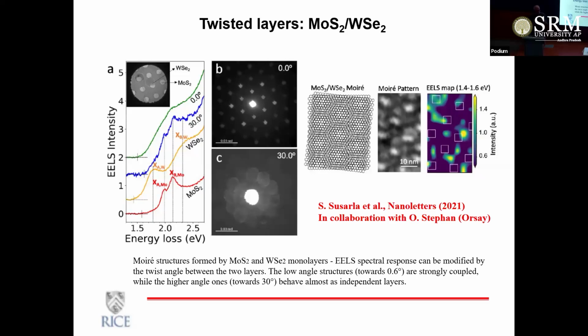You wouldn't typically imagine that twisting two films would be called engineering, right? But when the thicknesses are at the atomic scale, then you start to see significant changes in the electronic structure and physical properties by just twisting. Now, practically, it is a very challenging problem. How do you really twist at a certain angle when you have two layers that are atomically thin? Now there are robotic ways of doing this. People actually manage to twist exactly a certain angle called the magic angle, which has really interesting behavior. So again, typical engineering as we see it and engineering at the nanoscale are quite different. You're really doing things at the atomic scale. Small twists have a large impact on the behavior. A small chirality change in nanotubes has a huge impact on electronic structure. So that's the whole flavor of nano engineering that I want to convey.